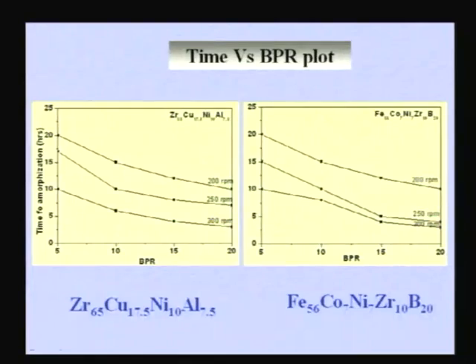And one can talk in terms of what happens when you put these powders into a ball mill and look at how various milling parameters affect the type of phases that are forming. This is one such example which tries to show you different milling parameters in ball milling. One is the speed of the mill, the RPM, and the ball to powder weight ratio. So, if you are increasing the speed of the mill, definitely you are increasing the energy, isn't it?